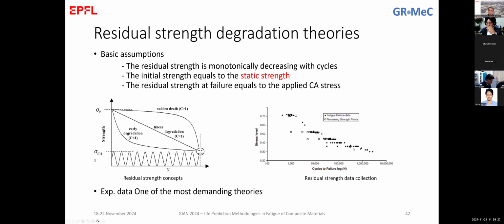And we've seen that this relationship is usually linear. So there is a linear degradation trend, but for many materials, it does not show any indication of degradation. So it doesn't actually follow this linear degradation in the sense of monotonic degradation. It is linear until a point where we have what we call sudden death. This is one of the reasons that these methodologies are not very commonly used, because, specifically for materials that are highly anisotropic, they do not give initial indications of failure during the lifetime. Another reason that these methods are not very common in practice is that they need a lot of experimental data.